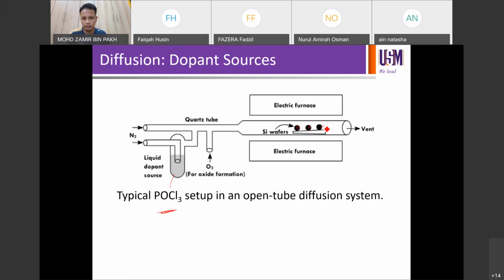So you're going to have your heater here, to heat up your chamber. It's typically done between 900 to 1000 degrees C. The process duration depends. It may go from 20 minutes up to 1 hour, 1 hour plus, at different temperatures, according to what you need.